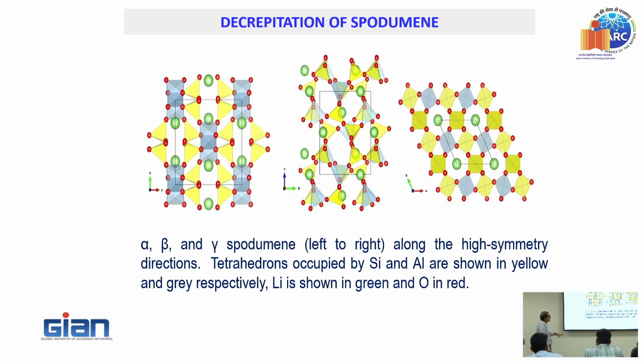See, spodumene as such in nature is available in alpha form. So this is very, very refractory, chemically inactive. In order to make it chemically active, it has to be loosened. Interatomic bonds should be loosened. So it will be converted from alpha to beta phase. This is more susceptible for leaching. So this is called decrepitation. This will happen anywhere between 900 degrees centigrade to 1100 degrees centigrade. This is called the decrepitation process, that is loosening.